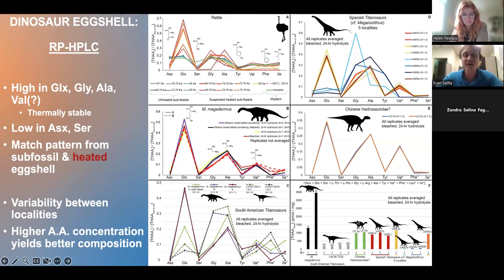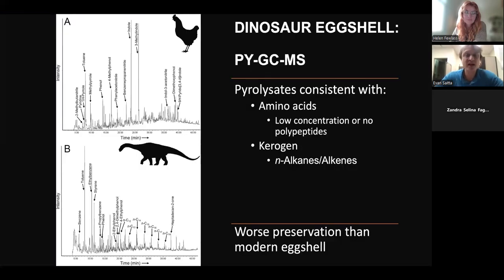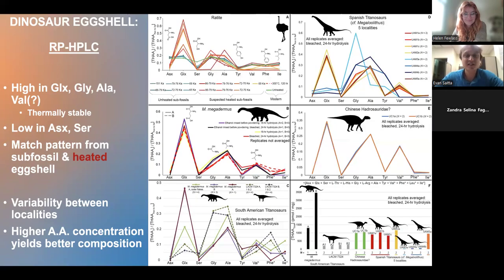The fact that you see it with the higher concentrations, the fact that they're fully racemized, suggests that they're ancient. The fact that you have other organic compounds consistent with very ancient organic material, this kerogenous organic geopolymer. The fact that you can use this bleach treatment to better isolate the intracrystalline amino acids. All of the groundwork that's been done by Penkman, Demarchi et al., all those people who have shown that the intracrystalline region of these eggshells can act as a closed system. It is very difficult because you're dealing with low concentrations, but that's why I use many different methodological approaches. If they're all consistent, then you can be a little bit more confident.